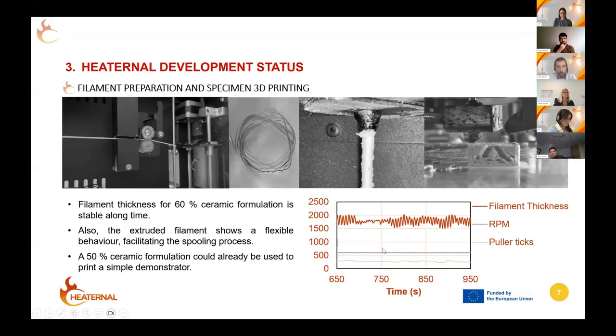Here at the bottom, you can see the stability of the filament diameter as it is formed, which is an indicative. Generally, a filament for 3D printing should be 1.75 millimeter thick or 2.85. In this case, you see that we are dealing with 1.75 millimeter, and you can see that the diameter is stable enough for it to be processed.